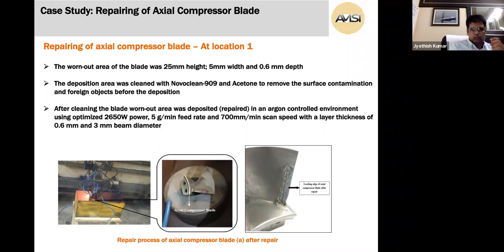Yeah. And some of the technical information, where we have used 5 grams per minute. Before this, we did a lot of characterization studies and process optimization of the LMD process to finally deposit the material on the worn out portion. So these are some of the parameters: around 2650 watt power, 5 grams per minute feed rate, and 700 mm per minute scan speed of the laser on top of the depositing layer, with a thickness of 0.6 mm and 3 mm beam diameter.